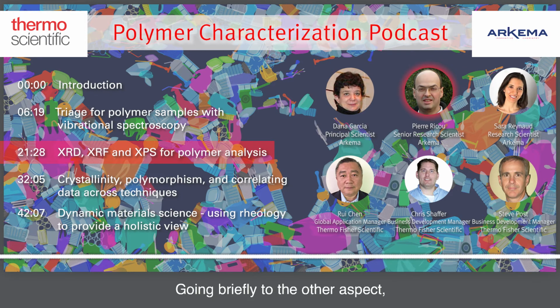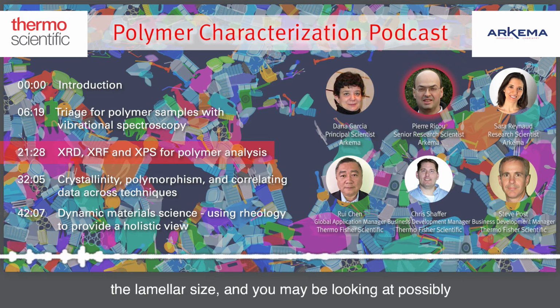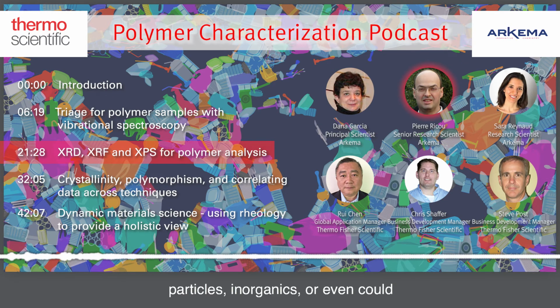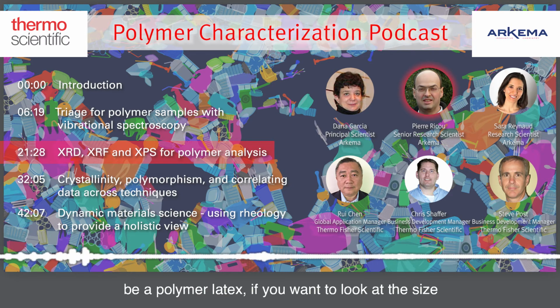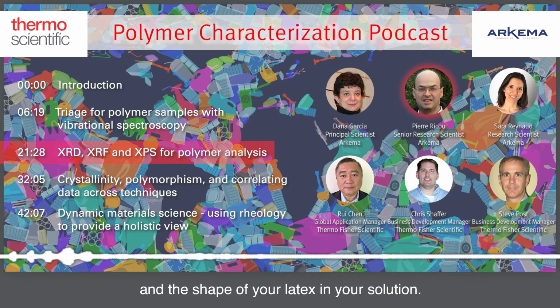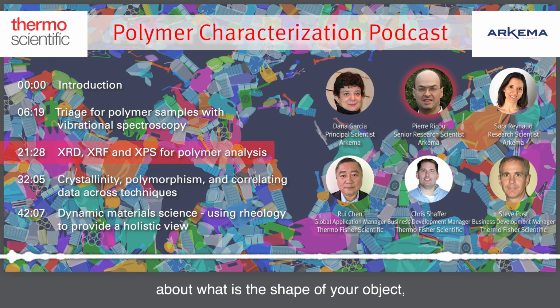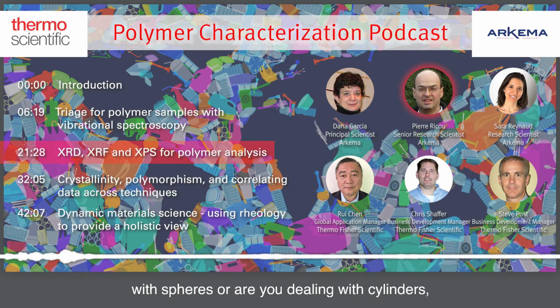And going briefly to the other aspect, which was ultra small angle X-ray scattering, those techniques allow you to look at even bigger objects. So now you're past the lamellae size, and you might be looking at possibly particles, inorganic, or even a polymer latex if you want to look at the size and the shape of your latex in your solution. Ultra small angle would be useful for that. Using a model for spherical particles, you can extract a particle size and a distribution as well. But it could also be used if you're trying to get some information about the shape of your object. You try to fit your signal to different models and figure out: are you dealing with spheres or are you dealing with cylinders, if you have nanotubes or small fibers in your system?